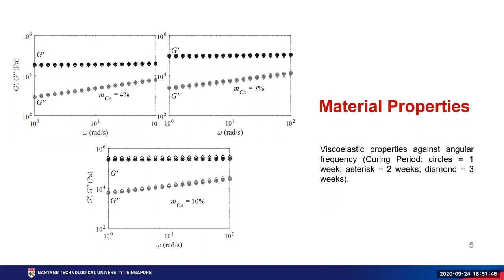The properties of these sheets were determined using a small amplitude oscillatory shear test in a rheometer. We determined two parameters: storage modulus represented by G′ and loss modulus represented by G″. Both parameters increase with increasing curing agent from 4% to 10%. From the rheological point of view, our material resembles a Voigt material, so the elastic modulus and viscosity were calculated from G′ and G″ by assuming a Voigt material assumption.